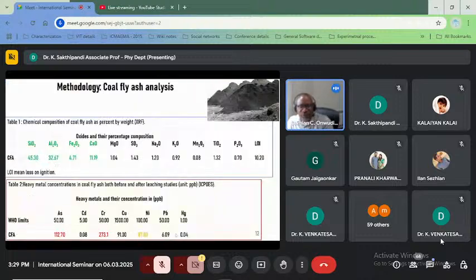Next slide. Next. The advantage of this coal fly ash is that it is highly rich in silica, in alumina, in iron oxide, and in calcium oxide. This material can be used to make ceramic membrane. So we did an analysis of the coal fly ash, and we were able to identify some toxic metals present in the coal fly ash using ICP-OES. And then we had to remove the toxic material and clean up the coal fly ash to be able to use it in the construction of ceramic membrane.